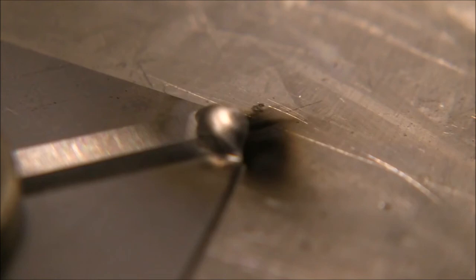But still, you can kind of work around it if you get that filler rod in there to compensate. So now that I've got a tack on both ends of this thing, let me light up on the other end, putting the sharp electrode back in there. And you can see pretty smooth start, and I kind of melted a hole right away. But after I get going here at only about 10 amps, things are fine.